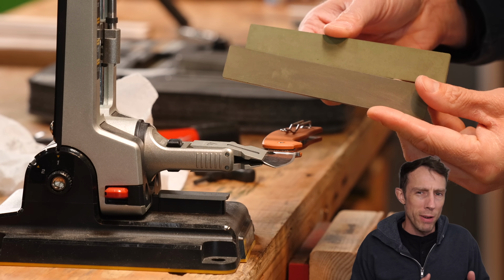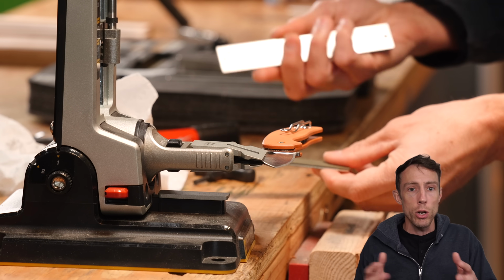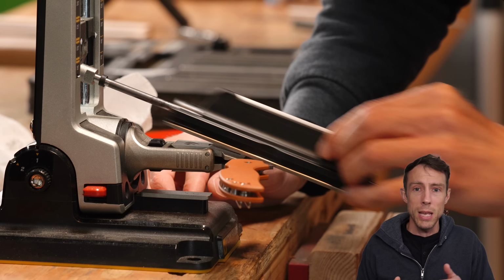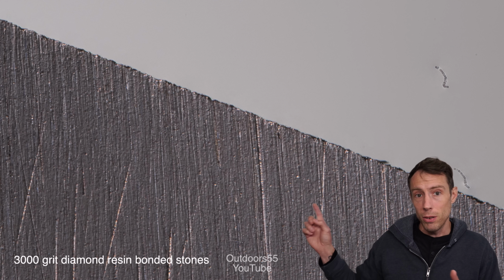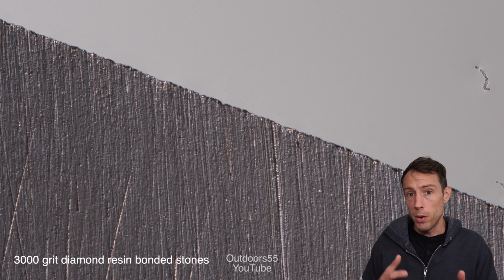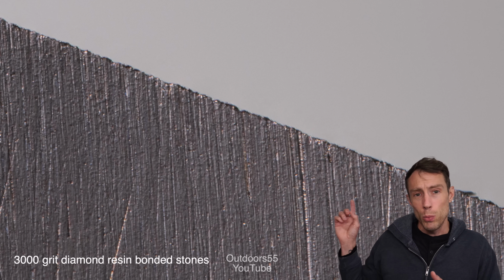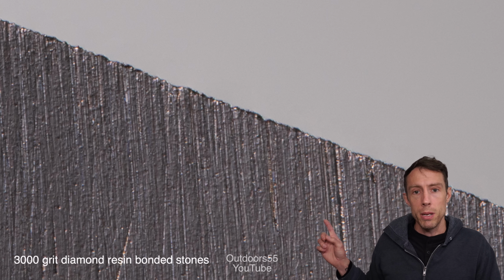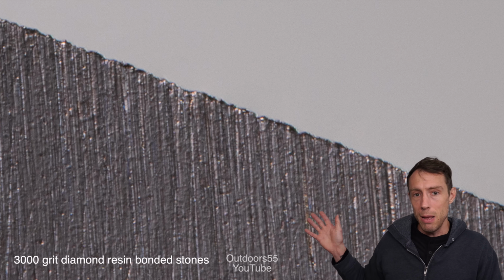Now, what about resin bonded stones? Well, I switched over to resin bonded diamond stones and took the apex to 3000 grit. And again, after looking at the apex right off of the stones, you'll see that we have points along the apex where we did form a burr on the stones, but as the burr was removed during the sharpening process, very small pieces of that apex went with it.